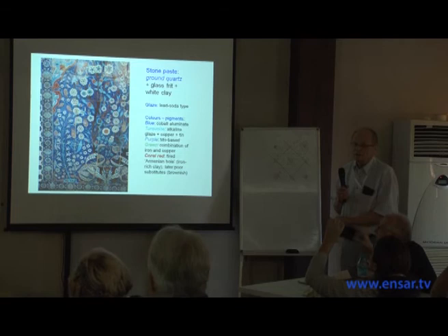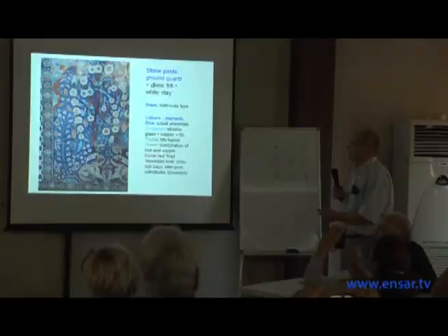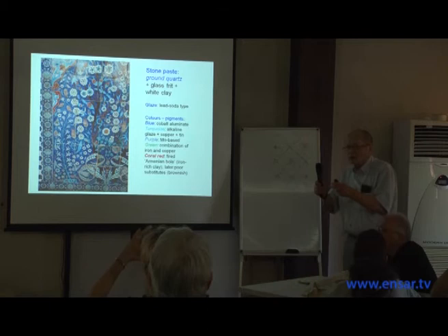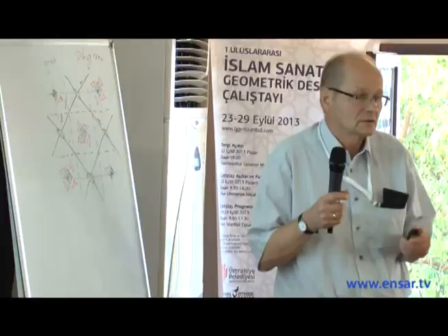And why? Because first, it was melting the glaze at lower temperature. Secondly, it gave more transparent glaze. And third, they say, when you cool things, you have thermal expansion. They shrink, and so they say they achieved that the glaze and bottom were shrinking at about the same rate. Otherwise, you get it cracked. Yeah, you have this craquelure. So that's why they did it.